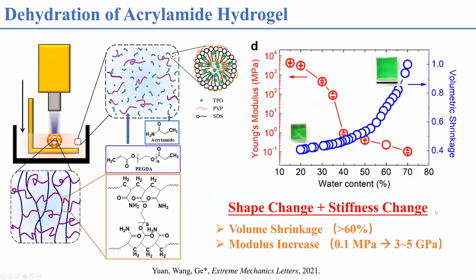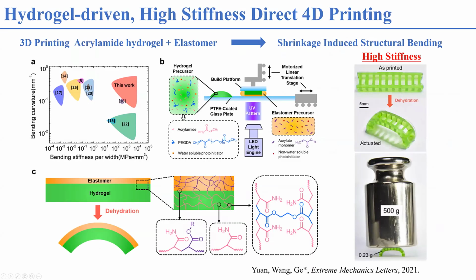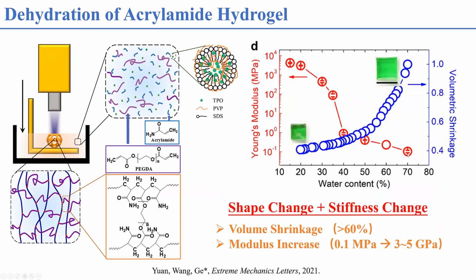And when we studied our acrylamide hydrogel, we found that once it loses water, you not only see a large volumetric change, but the modulus also changes a lot. When the hydrogel has high water content, it is very soft, maybe just 7 kilopascal. But when the hydrogel loses its water, there will be a glass transition in the hydrogel, and then the modulus is very high, not kilopascal, actually gigapascal, like 3 to 5 gigapascal. Therefore, dehydration is a process which is shape change plus stiffness change.